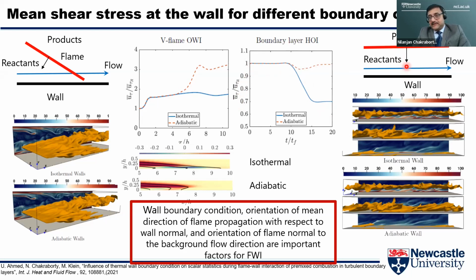In this case, the flame moves like this. Thermal expansion effects are mostly in the wall normal direction. As a result, the redistribution of momentum from the streamwise direction to the wall normal direction gives rise to this drop. But this drop is less stiff here in the adiabatic case. So the wall boundary condition plays a very, very important role. The orientation of the mean direction of flame propagation with respect to the wall normal, and the orientation of the flame normal to the background flow direction, all of them are very important in the case of flame wall interaction in a turbulent boundary layer.